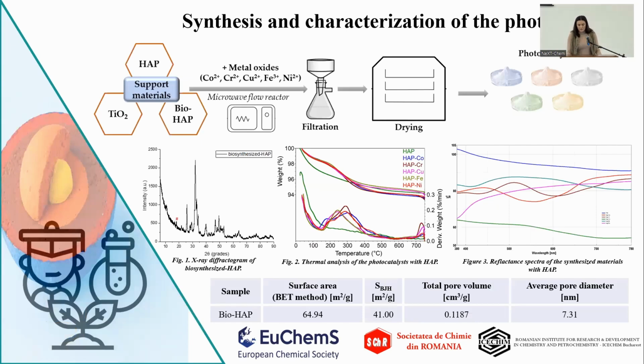depollution process. The first objective was fully accomplished because we obtained 3 sets of photocatalysts using as support materials synthetic hydroxyapatite, titanium dioxide, and biosynthesized hydroxyapatite, which we functionalized with 5 metal oxides of cobalt, chromium, copper, iron, and nickel. I want to mention that the biosynthesized hydroxyapatite was obtained using mussel shell waste, which underwent grinding, and then the powder obtained was calcined at 1000 Celsius degrees in order to obtain calcium oxide, which was further used for the synthesis process. The photocatalyst synthesis was done in a microwave reactor. This was followed by filtration steps, and then drying to obtain the photocatalyst we used in the